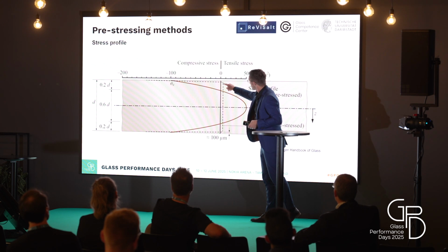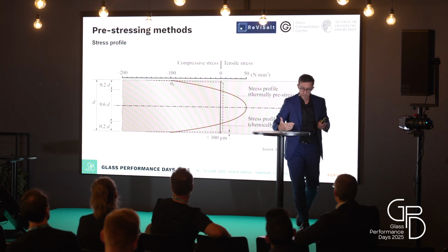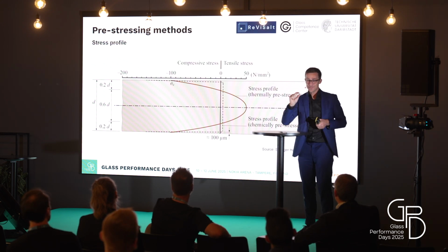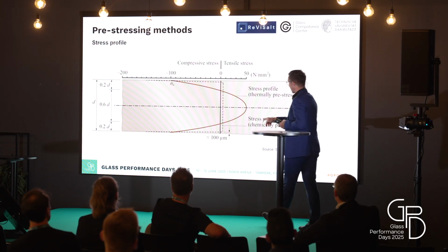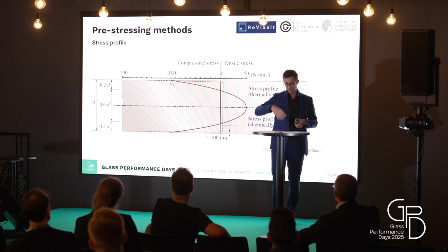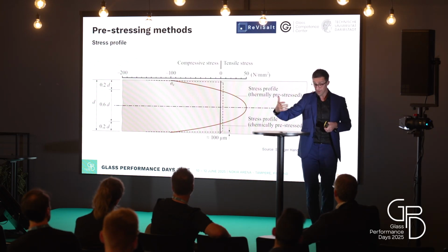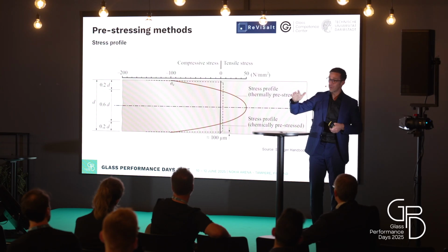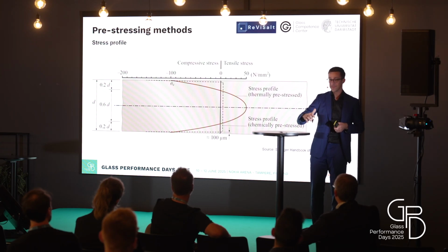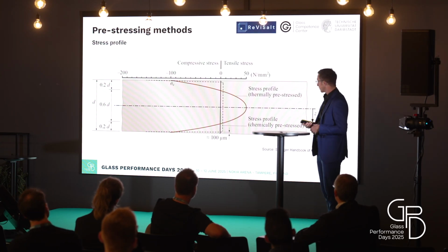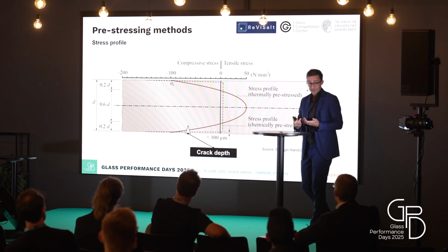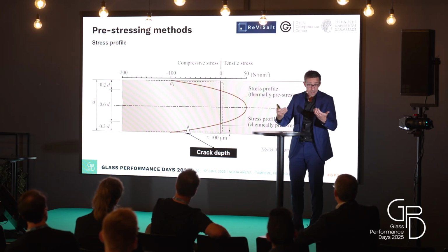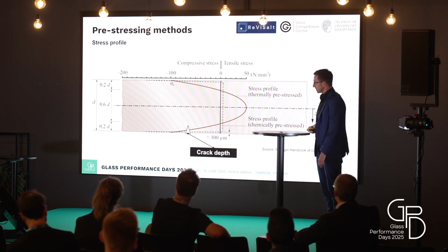Chemical tempering, this is the stress profile. It looks totally different. Here's 100 micrometer. This is possible for aluminosilicate glass and a little bit more, but not for soda lime glass. The border is, I would say, 50 microns, sometimes only 10. So now the question is, what happens if there's a crack and the crack is larger than the 10 microns? We have to think about this.